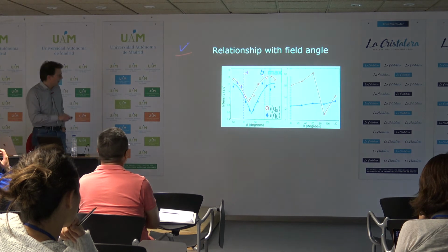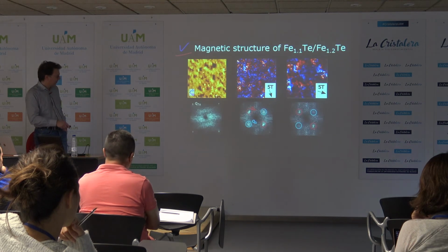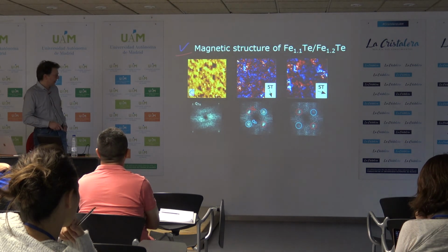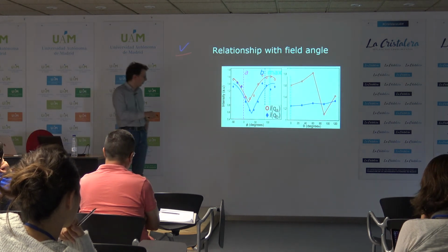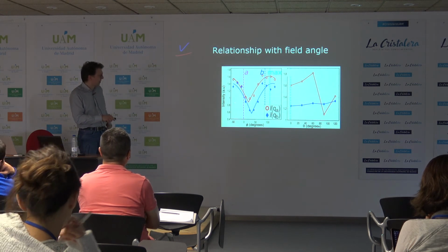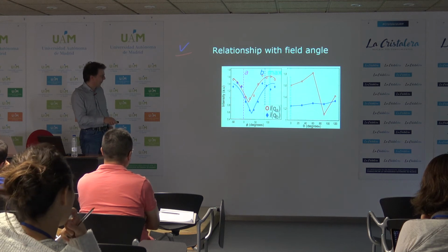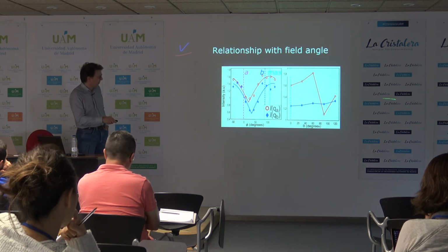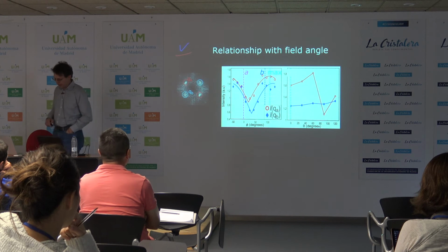For the in-plane angle, we can see that both these maxima disappear at the same angle, which tells us that for those 2 points, the spin direction points in the same direction. But for the out-of-plane angle, actually they behave quite differently. One of them behaves like a spin spiral, whereas the other one is suddenly suppressed once the magnetic field goes to an out-of-plane angle.